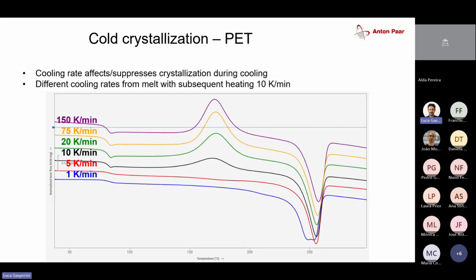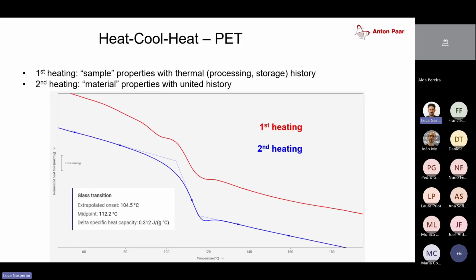And this is also visible in here, which is the glass transition of the PET. With the slow cooling rates before, we have actually prepared a highly crystalline sample, meaning the glass transition is quite weak. The step is not as pronounced as in the case of the sample that was cooled very fast and was created mainly amorphous because the crystallization didn't happen during the cooling. The crystallization then only happened during the heating. And whatever happened before, the sample always melts at the higher temperatures. And another example, I said that there are some special measurement modes or approaches that we can take.